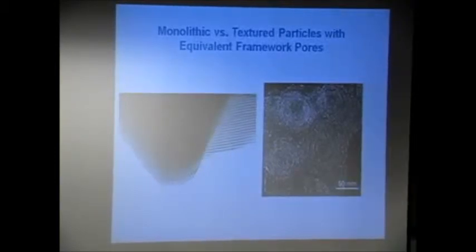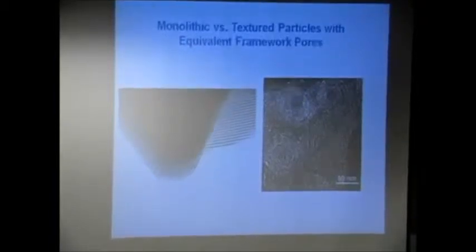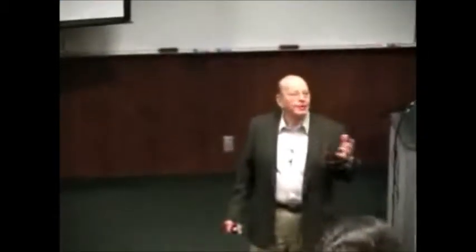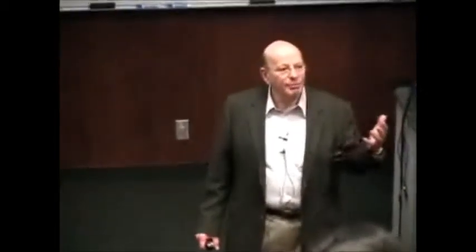Normally, the way one would control a path length of a porous structure is to make the particles smaller and smaller. But if you make them too small, where you minimize diffusion, you start making colloidal particles that are impossible to recover in an easy way. But if you design in this hierarchical structure of textural porosity, you keep the same size of the particle, but you make local access to the framework far more facile.